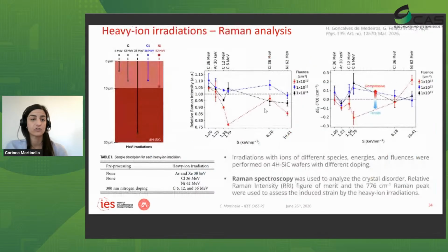Finally, I also wanted to show you this work. In this case, we irradiated devices with heavy ions. This experiment was performed at ANSTO in Australia using a microbeam. And we selected a matrix of different irradiations. So we had different ions with different energies and therefore different penetration ranges. And we were irradiating wafers. Again, these are the same wafers that are used to manufacture the components. But in that case, we had wafers with different doping.